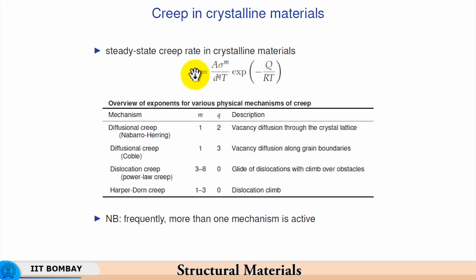So, the strain rate is significantly influenced by the stress and the corresponding dislocation activity, and then it becomes independent of grain size. So, 0 is the value of q. Dislocation creep, or the so-called power law creep, is entirely related to the dislocation movement, and it becomes independent of grain size, and so is the Harper-Dorn creep, which depends exclusively on dislocation climb.